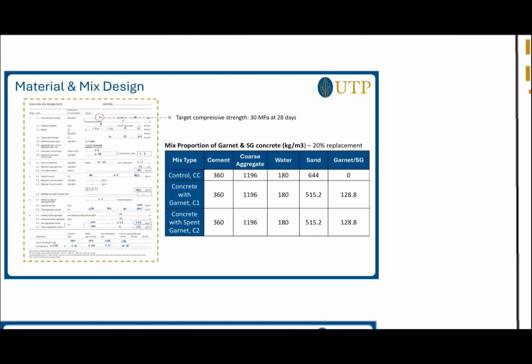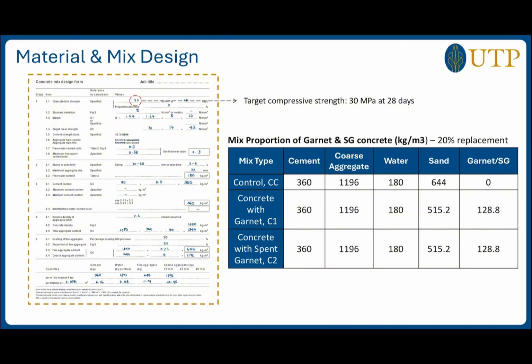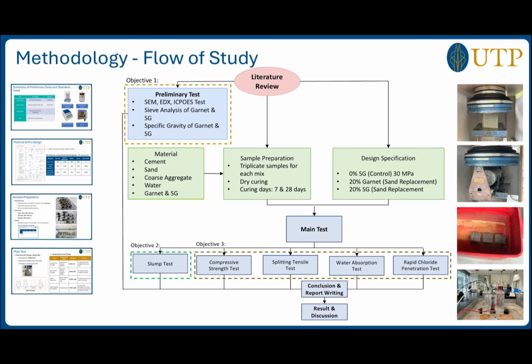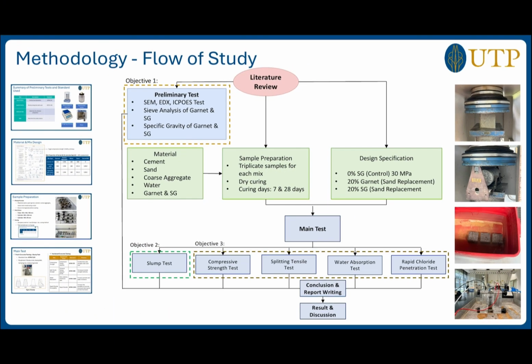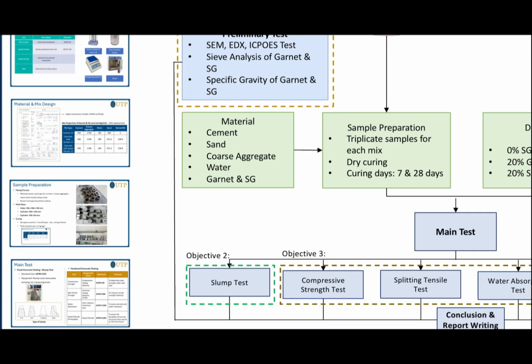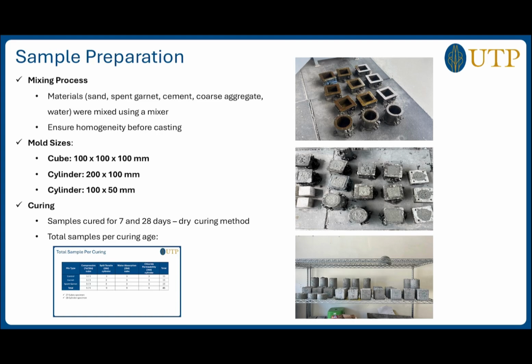And these are the details. So we target at 28 days, the compressive strength achieved 30 MPa. And these are the summary of mixed proportion of garnet and spent garnet concrete at 20% replacement. For sample preparation, each mix we have 3 samples, and for mixing process, all the materials were mixed using a